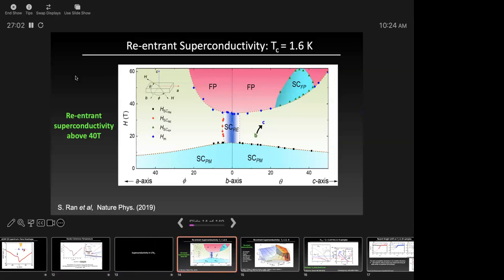Yeah, let's talk about superconductivity, which is the interesting thing in uranium ditelluride. The first thing I want to show you, you'll see why I'm showing this in a second, is that if you look at what happens to superconductivity in a magnetic field, you find something really extraordinary. We're so used to this that we say it in two sentences, but it's actually quite extraordinary. Usually when you apply a magnetic field, you kill superconductivity, and that's that. But in this system, you apply a magnetic field, and initially superconductivity does go down. But depending upon the direction in which you apply a magnetic field, you have another superconducting phase. This is called reentrant superconductivity.